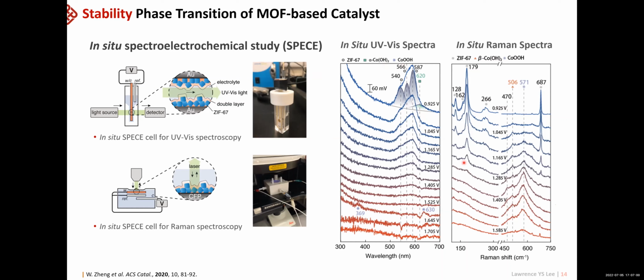A similar thing is observed in the in situ Raman spectra. Those ZIF signature peaks have disappeared at around 1.3 volt. Instead, we start to see the beta species, cobalt hydroxide, and also that converted to the cobalt oxyhydroxide. A very high peak until they catalyze the OER reaction.